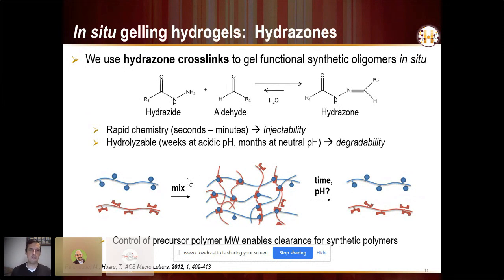The other benefit is that this is a hydrolyzable bond, but the hydrolysis happens pretty slowly. It's on the order of days to weeks at acidic pH environments in the body. It can be months at neutral pH depending on the crosslink density. So again, we have a lever we can use to do environmental responsiveness, but also keep these gels around for a long time. Of course, these are synthetic polymers, so the backbone is not degradable. They're carbon-carbon backbones, whether we work with zwitterionic polymers or with the PEGMA-based polymers. So to make sure that they can be cleared over time, which is another key translational barrier, we keep the molecular weight very, very low, below the kidney cutoff. As the hydrazone bond degrades, we regenerate these starting materials, these oligomers, which have low molecular weights, and we have evidence that these are actually cleared through the kidney over time.